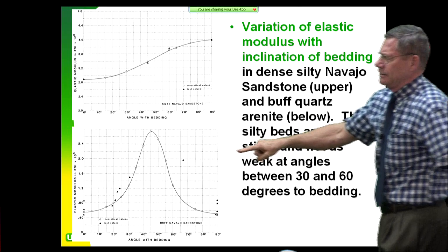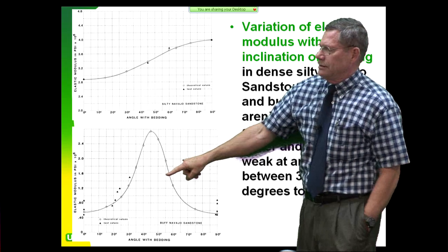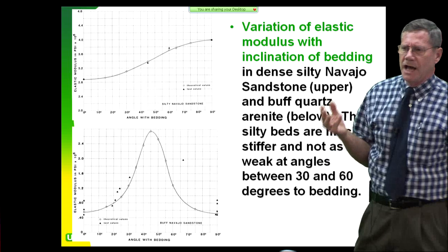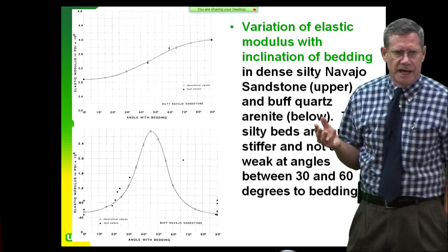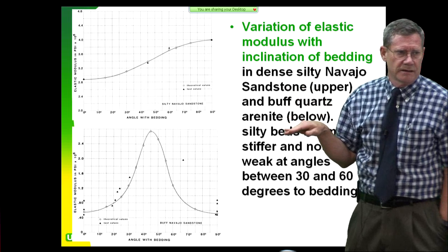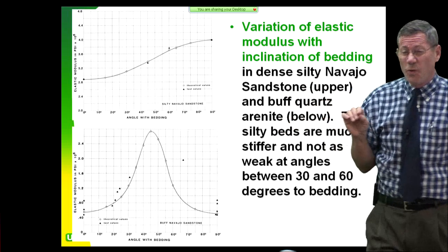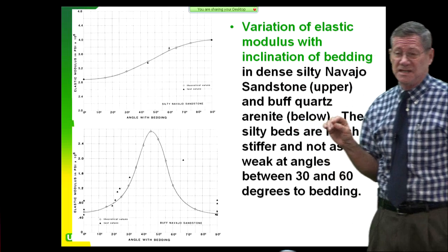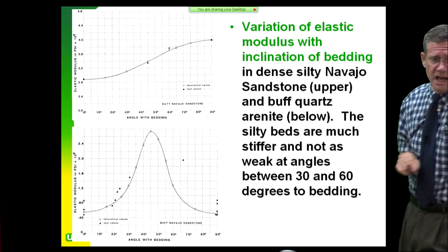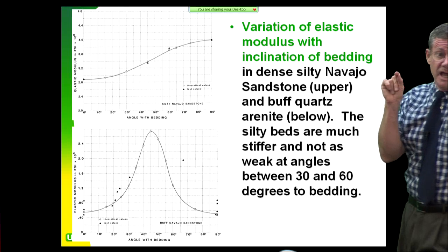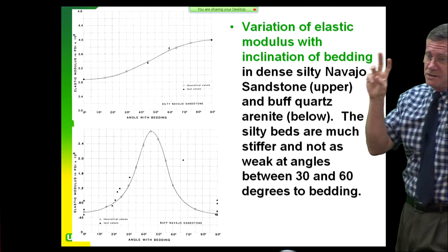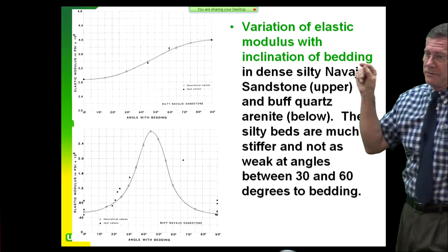This material is leached of its iron cementation. That's why it's buff colored. And a lot of it's also leached of a lot of its carbonate. So it's low tensile strength, like 1/40th to 1/70th the compressive strength. Now, the Griffith failure criterion, which we assume in all of solid mechanics and civil engineering, is 1/8th. T0 is 1/8th of compressive strength in two dimensions, 1/12th in three dimensions.